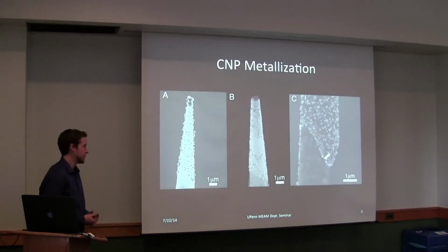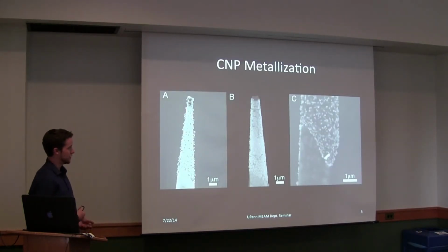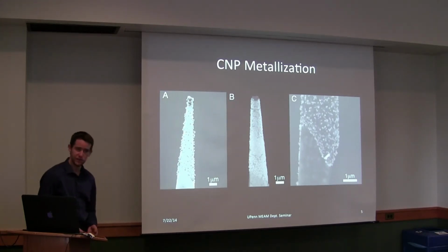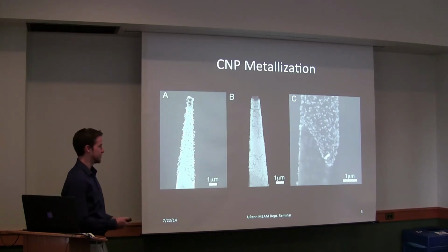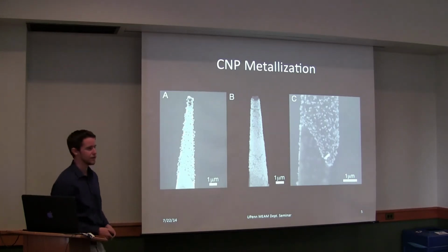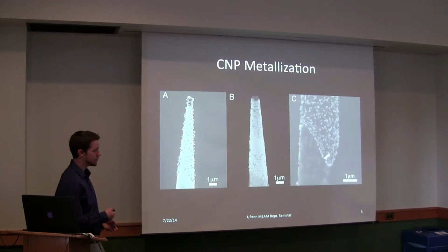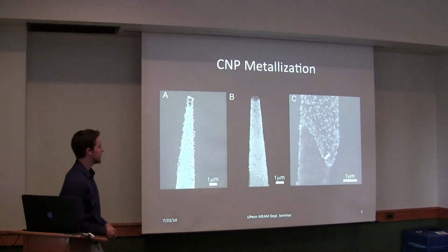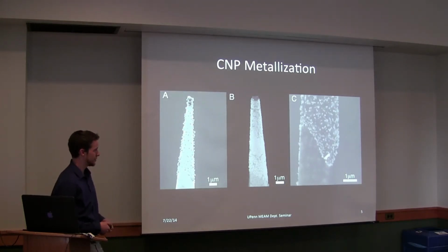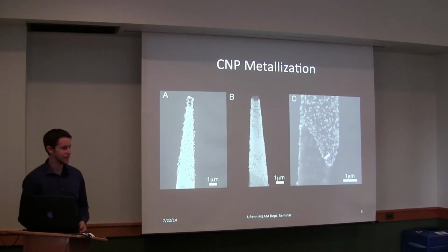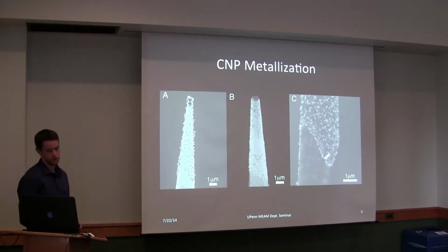You can also look to functionalize the surface with things like metals. For example, here we looked at depositing silver onto the CNP tip. If you wanted to change the surface chemistry of your electrode, or if you wanted to functionalize it with, say, some antibody that has a known surface chemistry that works with silver, but not with carbon, you can do things like that. These are two examples of double pulse electroplating, and this is pulse current electroplating, just showing that we can use these different techniques at this scale to get a nice surface coverage of silver.